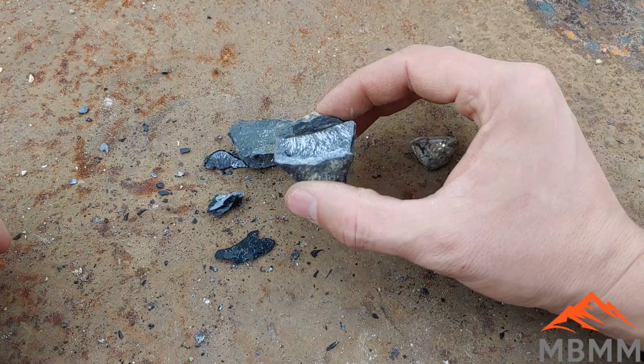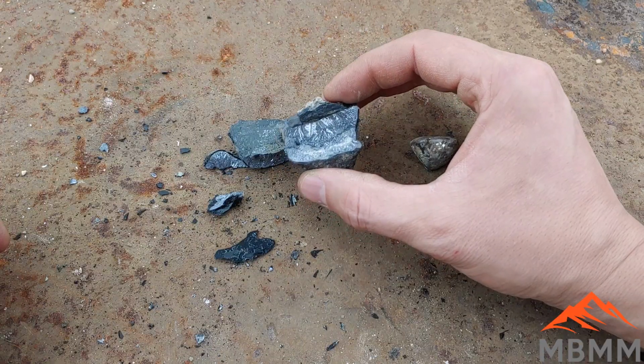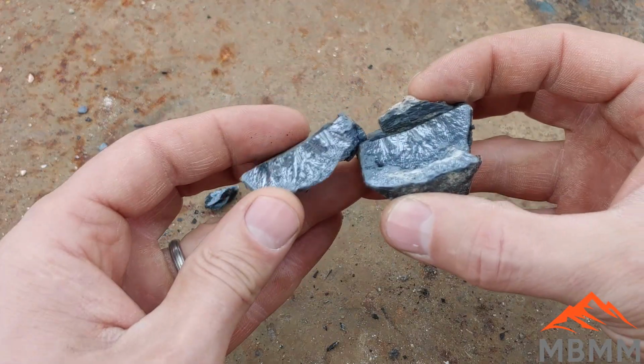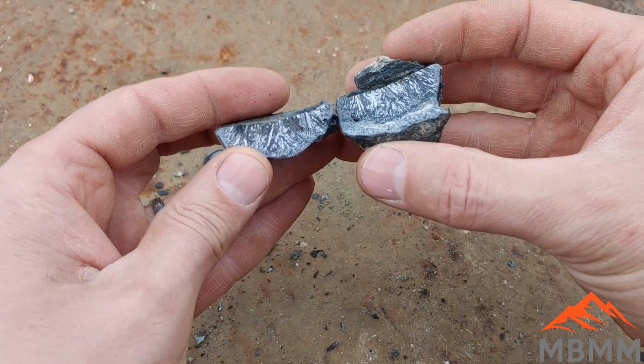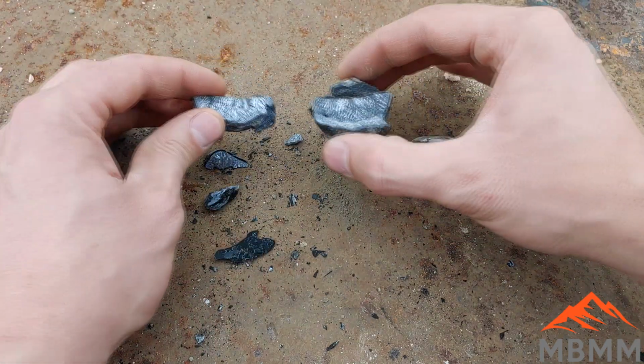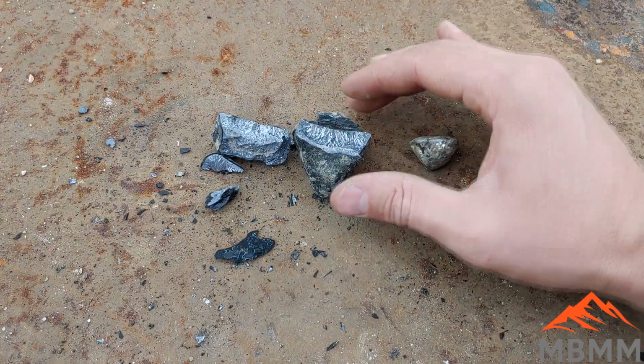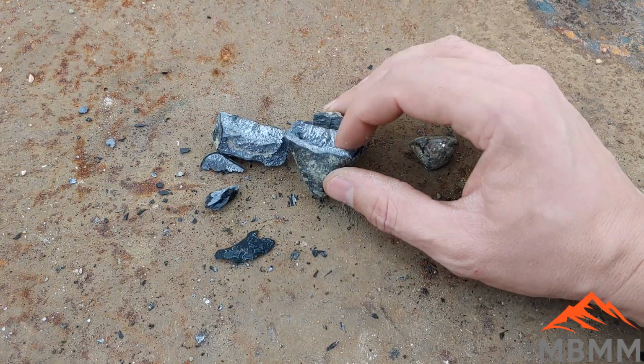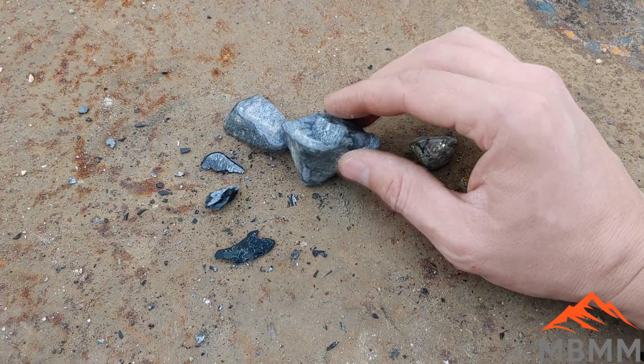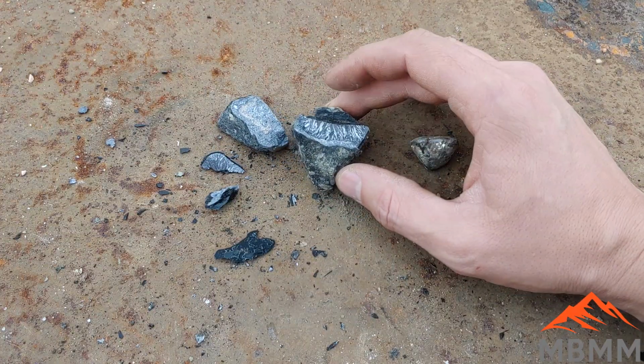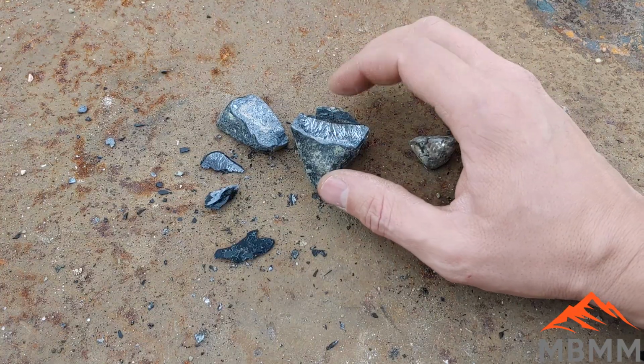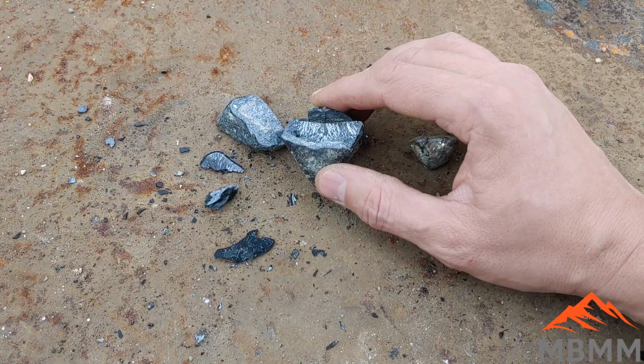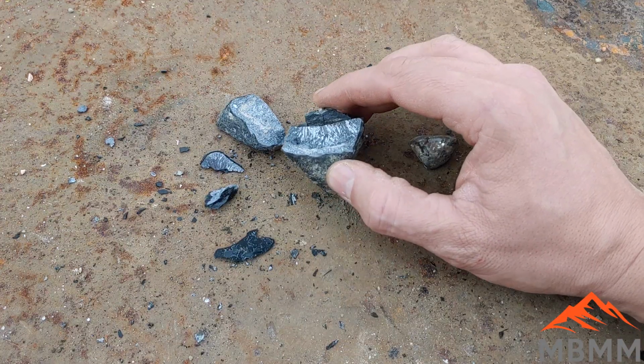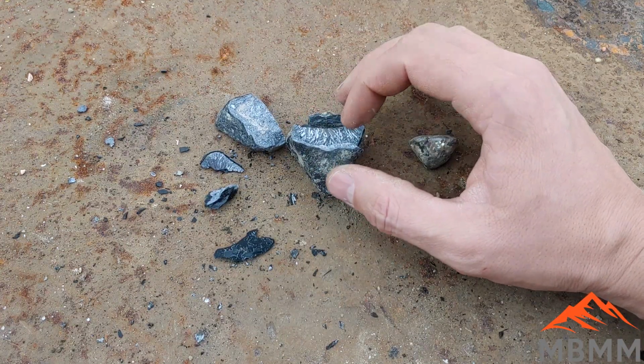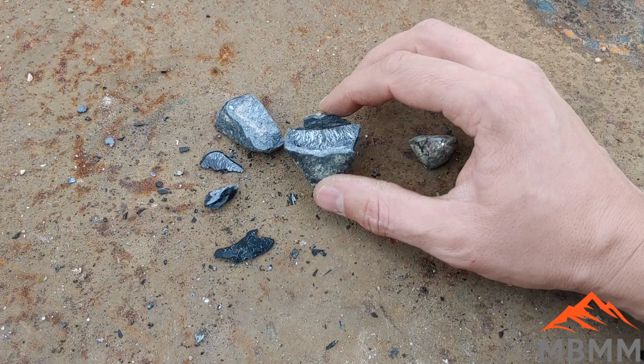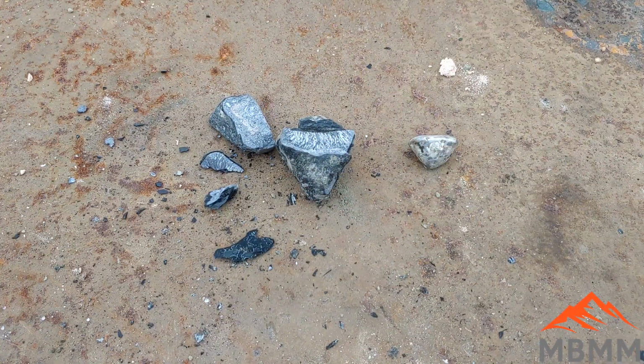And then this one is from the oxide stuff that I scraped off the cupel, and it's really pretty interesting. I had 300 grams to start with. I ended up with 250 grams of this stuff, and it looks like it's lead and iron mixed. It's not pure lead. It's not soft. It's real brittle and hard. So if you guys have any idea, that should have been pretty well oxidized, and I should have scraped that off, and it should have been absorbed by the borax. I'm not quite sure why it was still in the metallic iron form. But let me know what you guys think. And now we'll go take a look at the silver block.